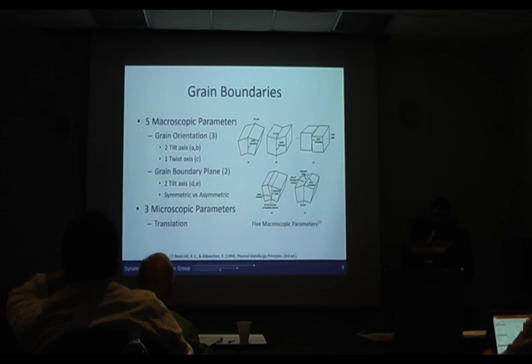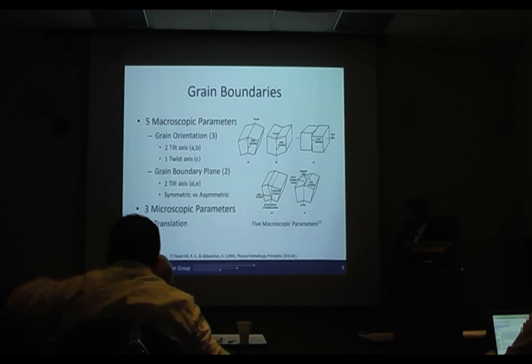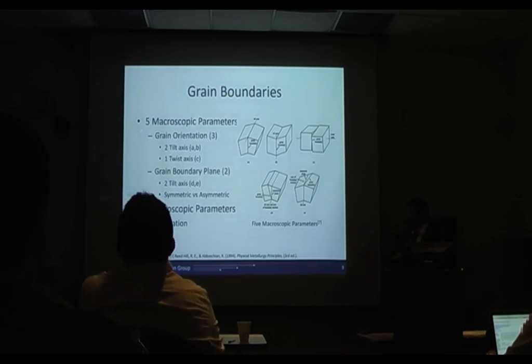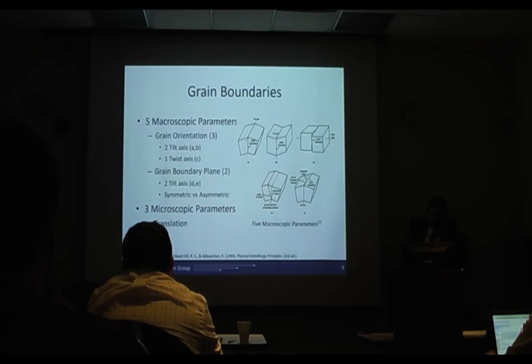Slide 9, Chad. So the question is, we see the grain boundaries are being attacked, and we want to know what's different about the different types of grain boundaries, and first we have to know how to describe them. There's 5 macroscopic parameters and 3 microscopic parameters. The macroscopic parameters are again divided up. You have your grain orientation, so each grain is its own crystal, and those crystals can be tilted in 2 axes relative to each other, and they can also have a twist. And then the grain boundary plane, where those 2 crystals actually meet up, can also be tilted in 2 different axes. The microscopic parameters are small translations in 3 dimensions that are a fraction of the unit cell.